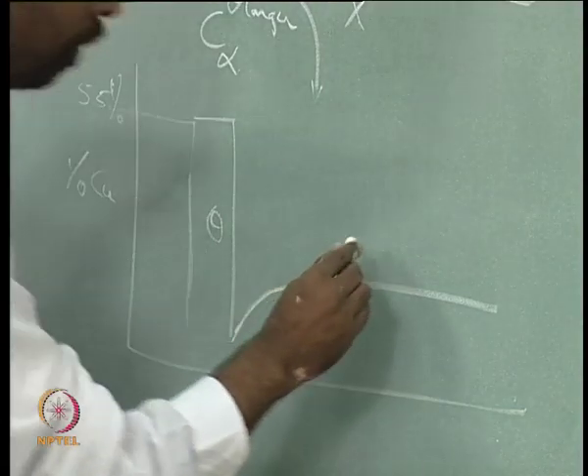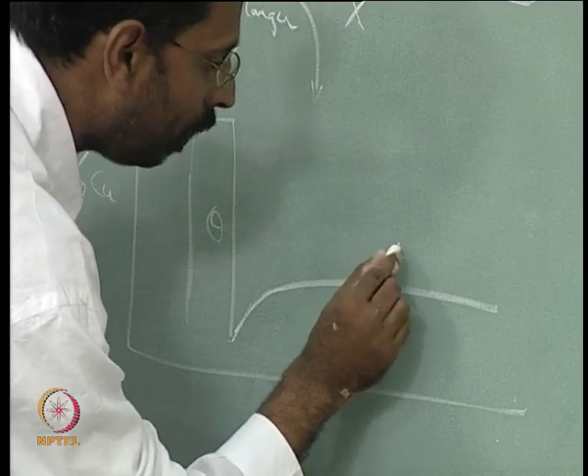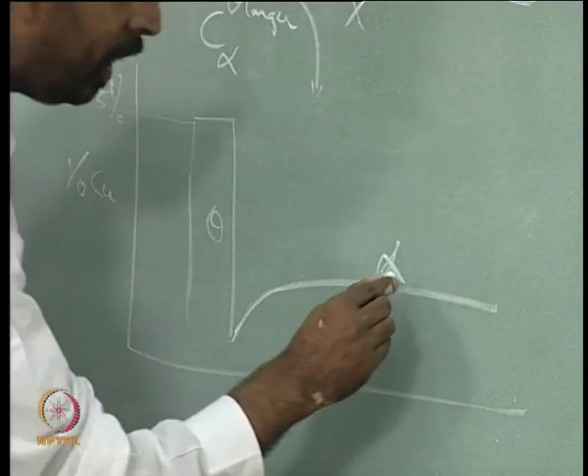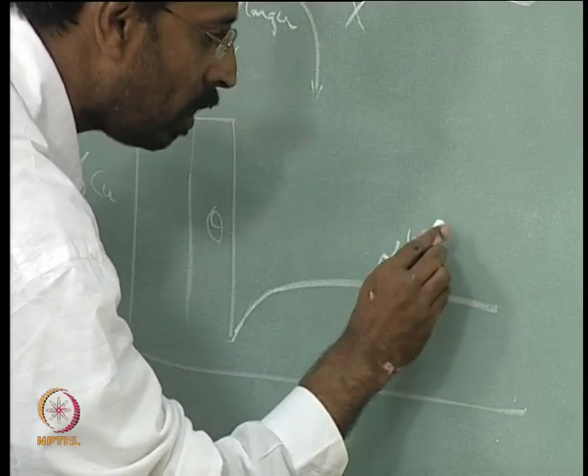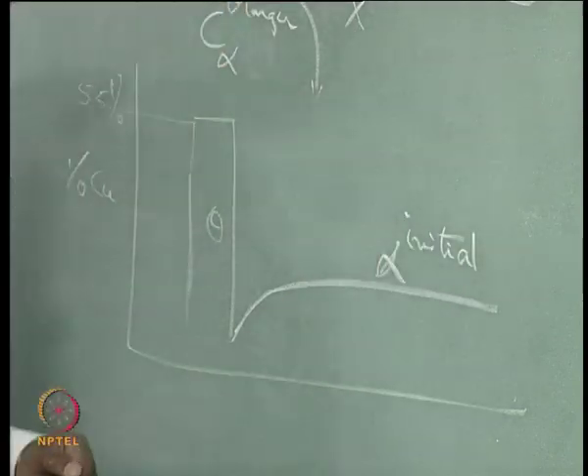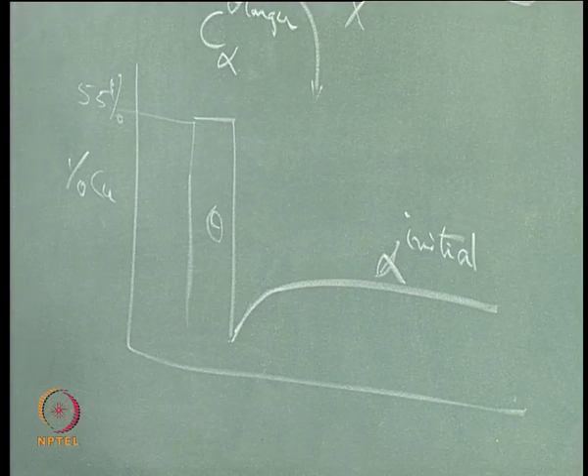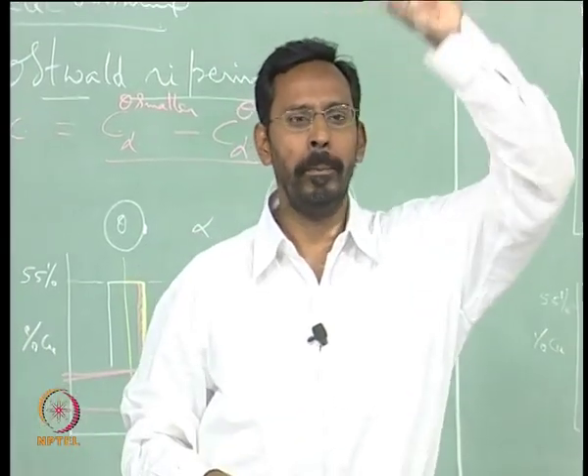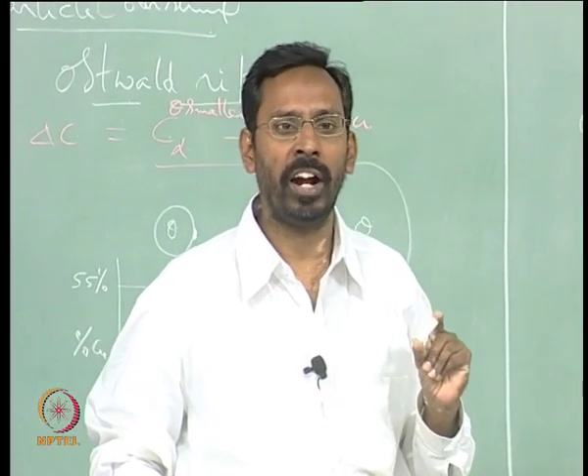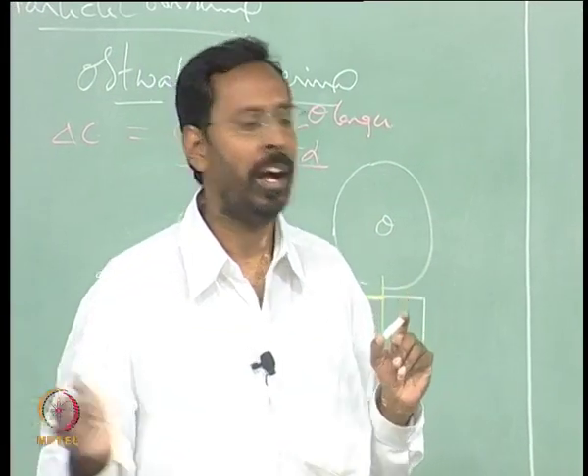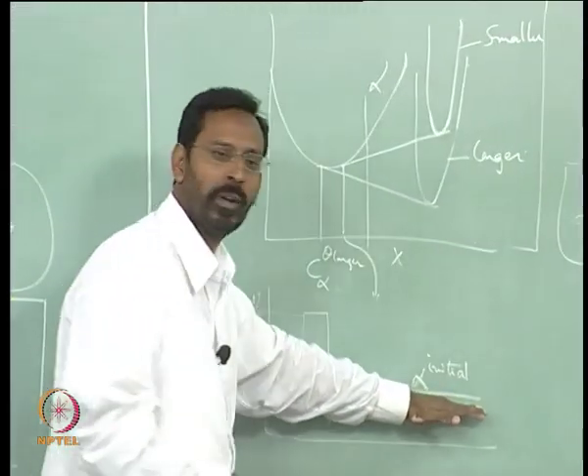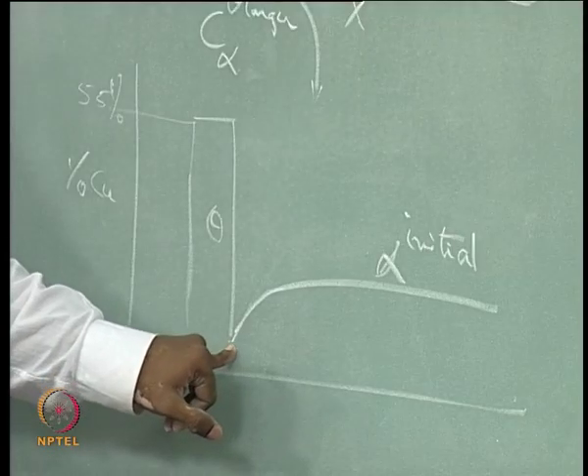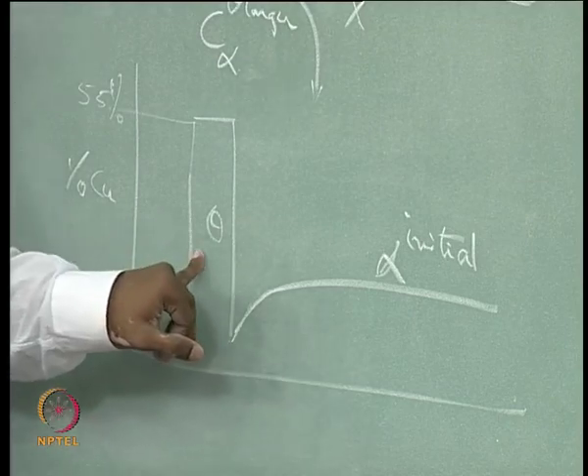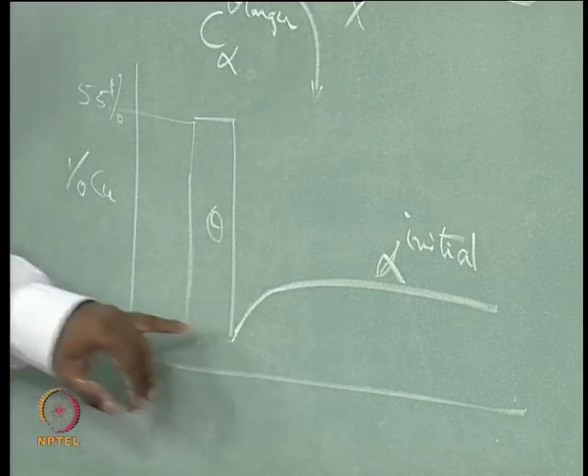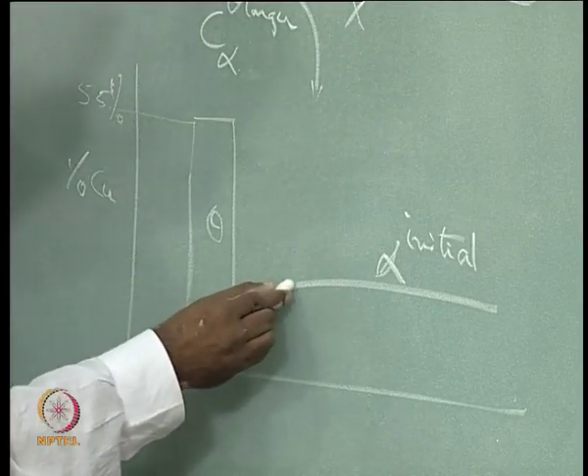This is the percentage of copper, this is the alpha of the initial alpha, the alpha with which you have started. You have taken an alloy of 4% copper, made it into a solutionized condition and then quenched it, and from there the actual precipitation has started, and that particular alpha is that 4%, but the alpha which is in touch with the theta is actually smaller, and because it is smaller, now you see there is a gradient here,